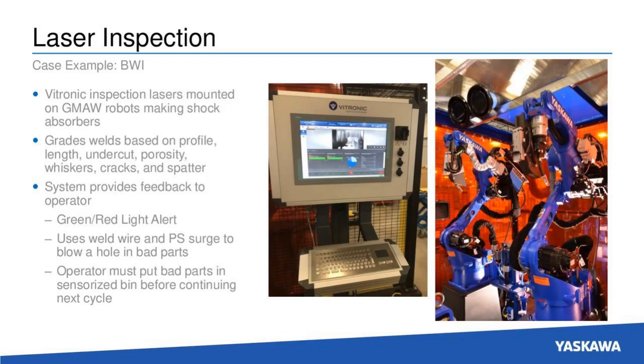If it's not the correct part, it'll sound an alert, of course, and give you a red light to show a no-go situation. But then after the scan, they get a grade. You can kind of see the HMI presented here in the middle of the screen, and it gives them a grade on each of those welds. And they're looking for the profile, the length, the undercut, porosity of the weld, if there's any whiskers, cracks, and if there's excessive spatter. So that data is then stored for that weld, for that part.